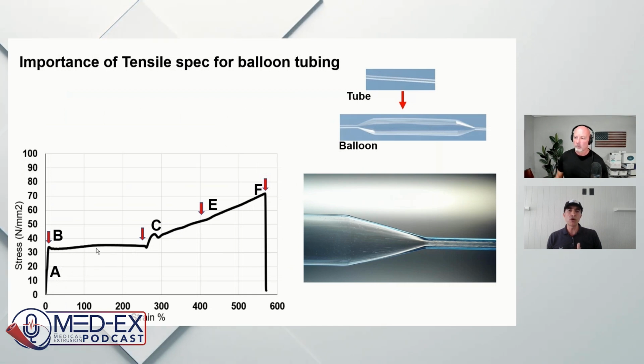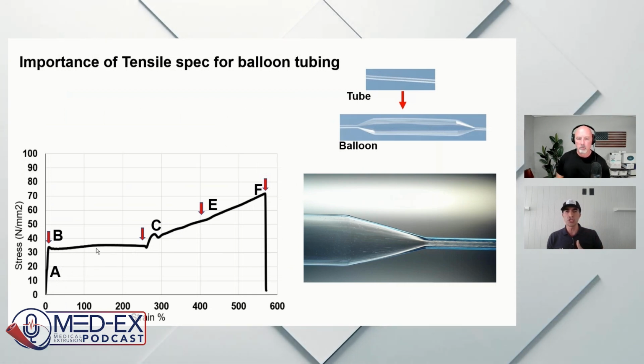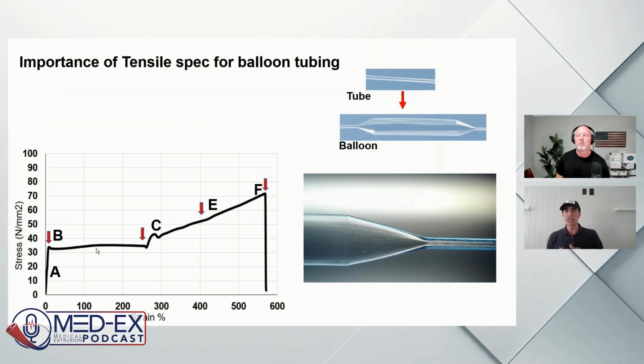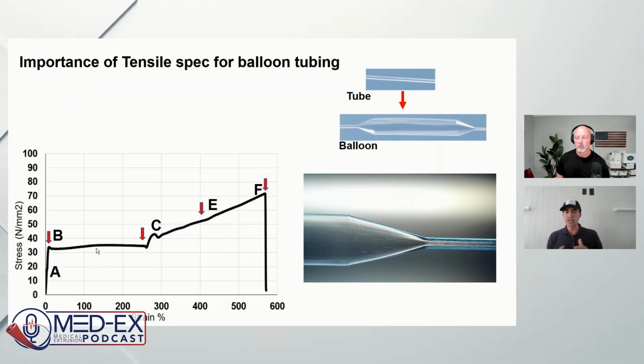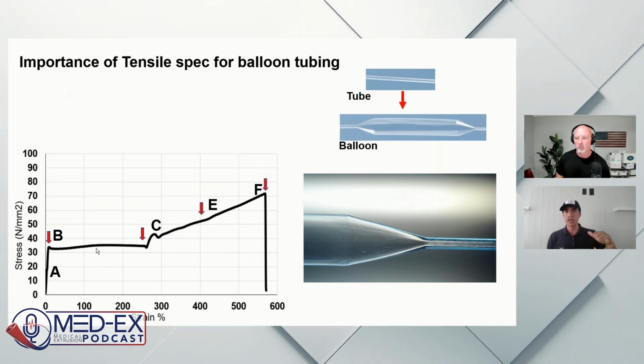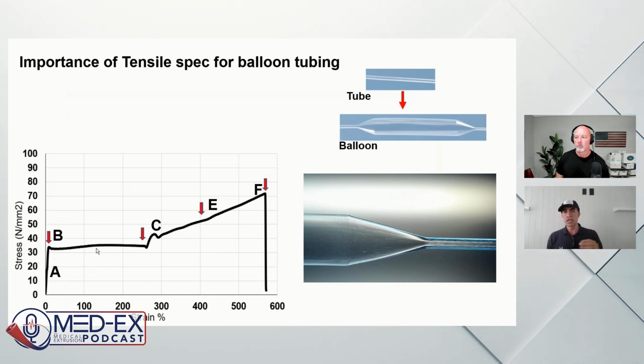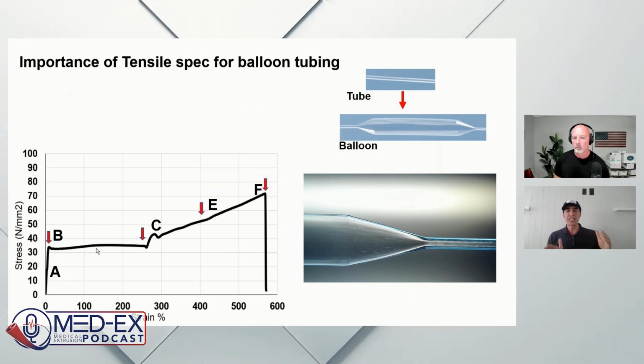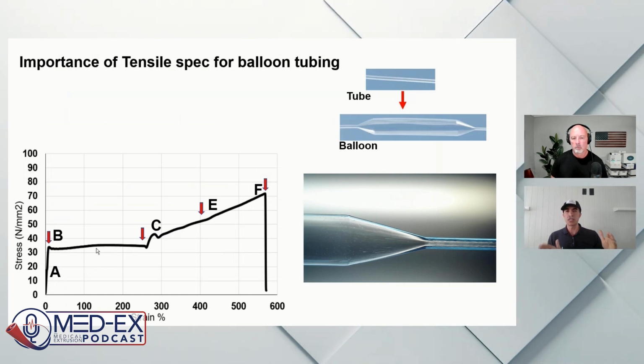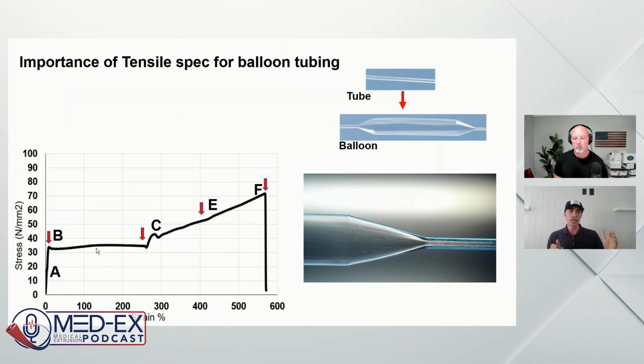And point C is when all the tube is finished, formed into the stretched tube, and strain hardening started. So basically now there is nothing for the tube to transition to, right? So they start to resist stretching, and that's why you get a slope. That slope would determine the resistance of the material to stretchability. And analyzing that region from C all the way to F, that's where we can define a nice tensile spec for the tube, right? That's where we can relate that to stretchability and molecular structure, basically.